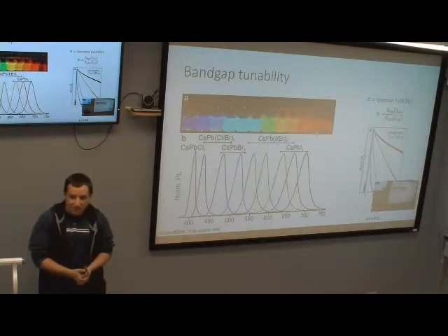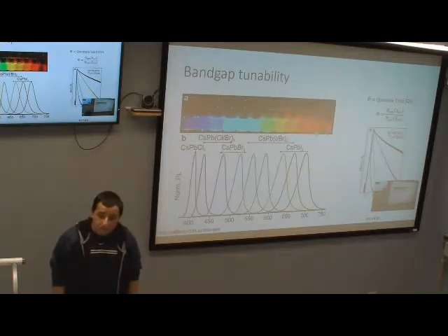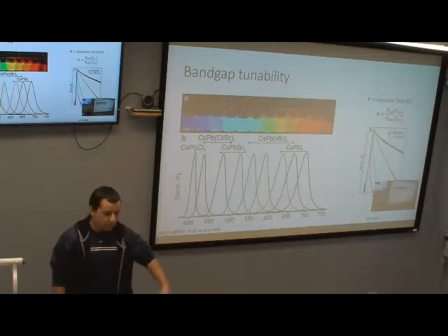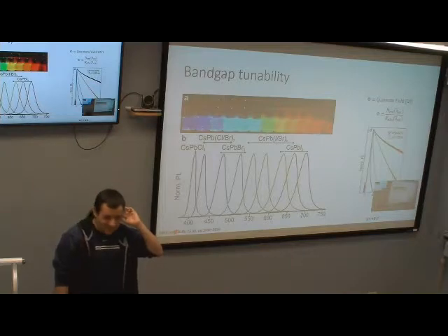It is also a function of charge carrier density. So if you already have like 2 electrons in a nanocrystal at one time, if you add a third, that's going to reduce your quantum yield because of higher order effects. Isn't it like adding a third, then you have to take into account Auger recombination? Exactly, that's what makes them less efficient.